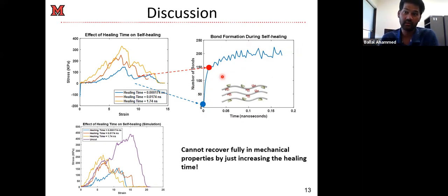In our case, the main resistance during the tension test comes mainly from these crosslinkers. So when you have a large number of bonds, for sure you have more resistance, I mean, the properties will be better. In our case, when the self-healing time is very low, at something like 0.0174 nanosecond, you are very close to the origin. So you have a low number of bonds and low peak stress, and when you allow more time for the material, you have a large number of crosslinking bonds, so you have better properties.